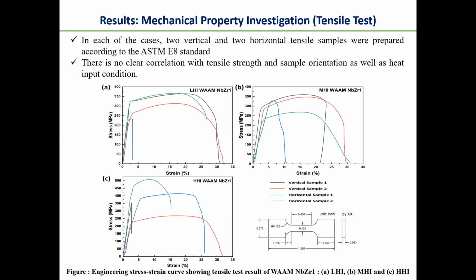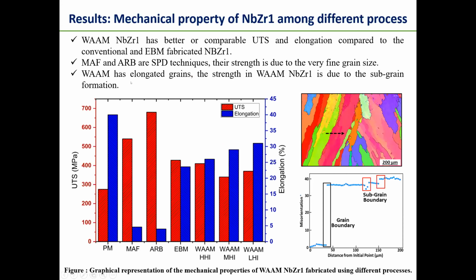Niobium zirconium is a ductile material. Most of our tensile samples failed in ductile failure, but some of the specimens failed in brittle failure. This may be due to the impurities in the component. And this is a summary of our tensile data with respect to other studies.